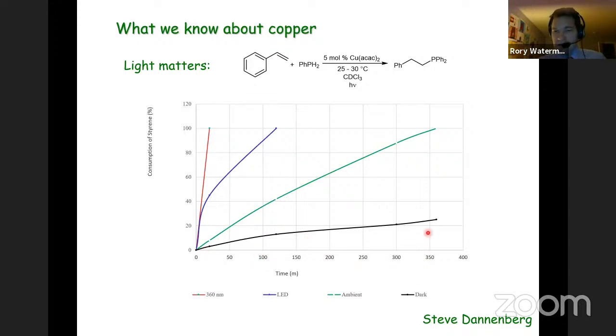If we deliberately run the reaction in the dark, there is some background reactivity. So this will thermally convert at ambient temperature to an extent. It just won't be very effective. And then, of course, LED and then UV light accelerate this. So just direct irradiation, increasing the photon density essentially with an LED bulb or increasing that energy with a UV bulb. And so you can make the choice about how much you would like to prompt this reaction, but it will simply turn over.